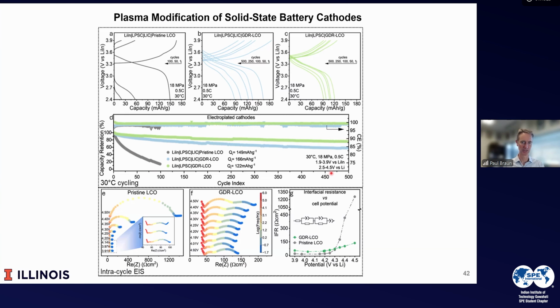And this is very aggressive. This is up to 4.5 volts versus lithium. And what we see is in pristine LCO, the resistances are increasing dramatically. While if it's treated, as seen by EIS, you see that the resistances increase only very slowly. And so indeed, this shows that in a solid state design, this surface treatment is even more important because there's an interface between the solid electrolyte and the cathode, and all of our treatment is occurring exactly at the surface, which provides a much improved cycle life.